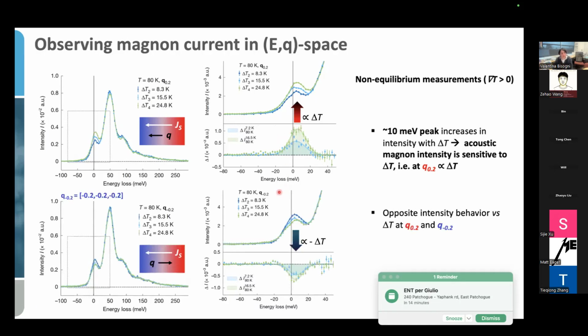Now let's do this test. Let's now switch the direction of momentum. So before, momentum was parallel to the magnon current. Now let's see what happens when the momentum is anti-parallel to the magnon current. So we repeat the same type of measurement for the same type of temperature gradient. And now what we get is that the RIXS intensity is decreasing as we increase the temperature gradient.